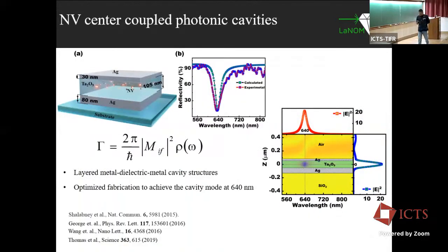So let's move to the experiment now with a few more single NV centers. We wanted to have photonic cavity structures at 640 nanometer. So first we start with a very simple cavity. We call it a metal cavity. You have a substrate, an 80 nanometer silver layer, then a 100 nanometer tantalum oxide layer with a lot of NVs dispersed. And you have a 30 nanometer top layer, because it has to be very thin to get the light out of the system.